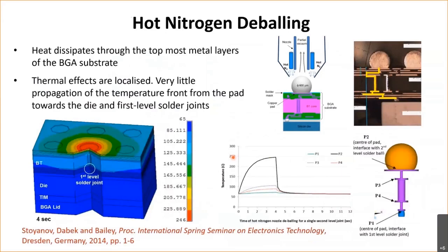Hot nitrogen deballing, these are for BGA components. The question being asked was, yes, we need to remove the balls and then place compliant solder balls onto the package. But this is, again, a temperature load. What would be the influence of this process on not the second level solder joint, but the first level solder joints? So this is really a simulation identifying how the temperatures change, and here we can see the second level solder joint on the pad. Of course, that's quite a high temperature change as that ball is removed. But what was good to see is not such a big change at the first level solder joint, which could be a different solder. So there's an example of how we've used modeling